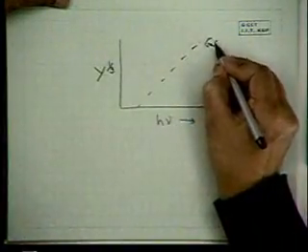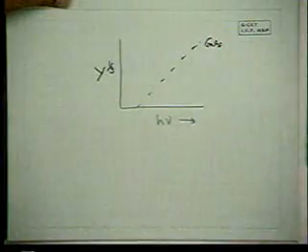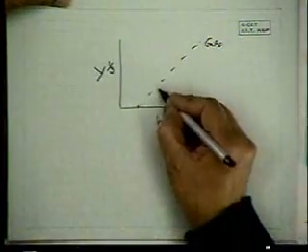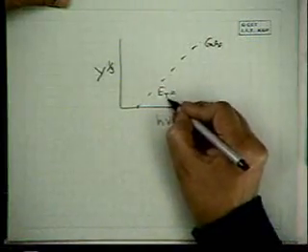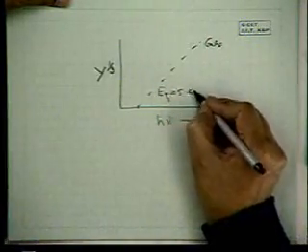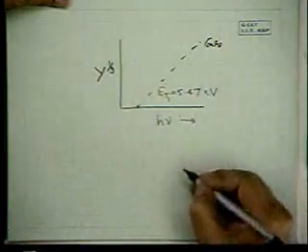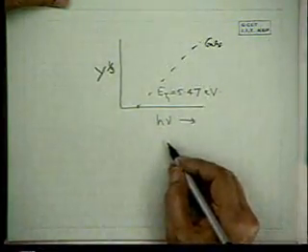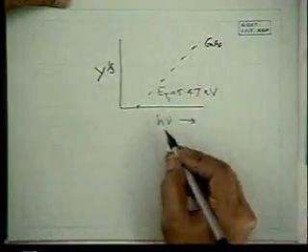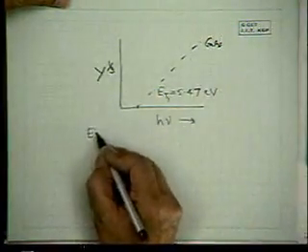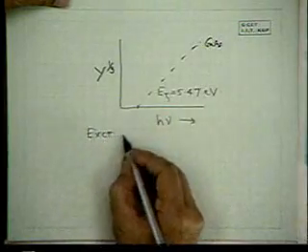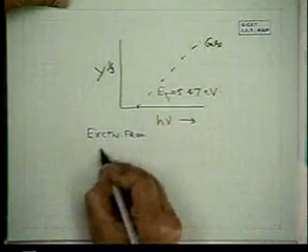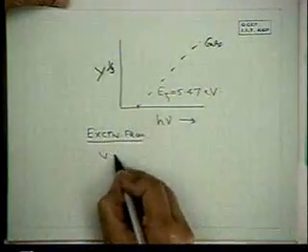for gallium arsenide, and this first threshold energy ET1 is 5.47 eV. This is from emission from the valence band. So one can ask, where does the excitation occur from? Excitation from the valence band.